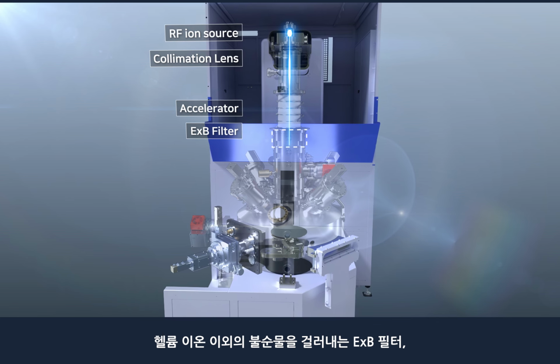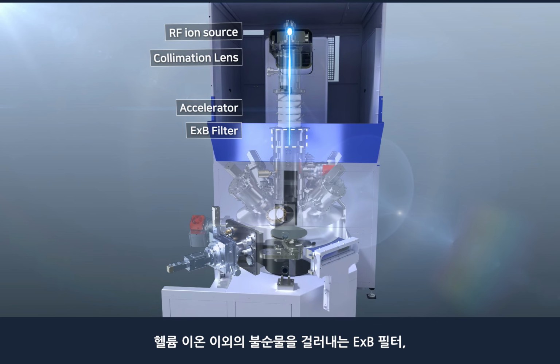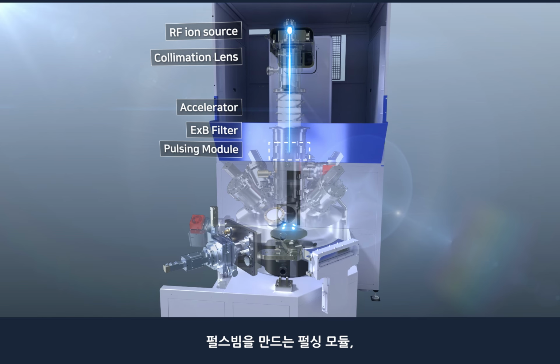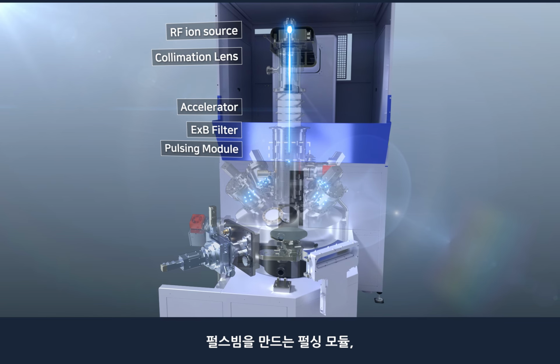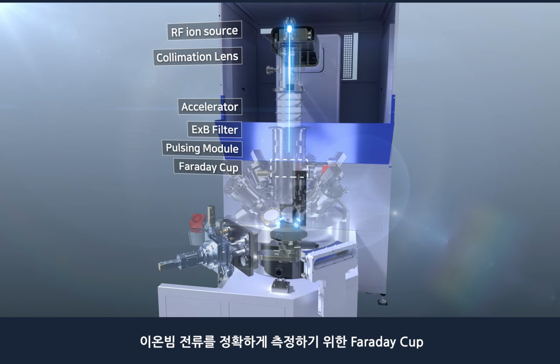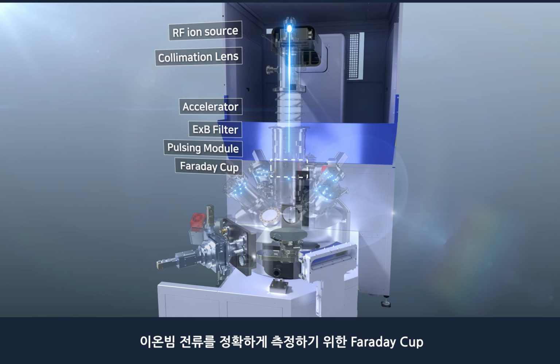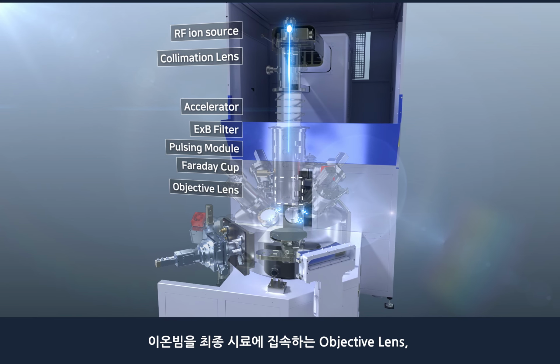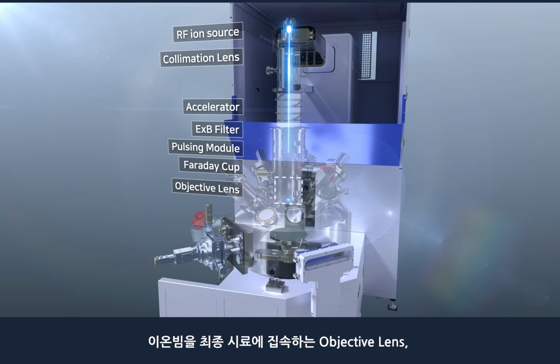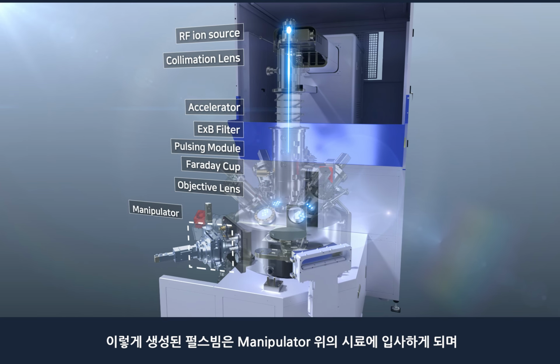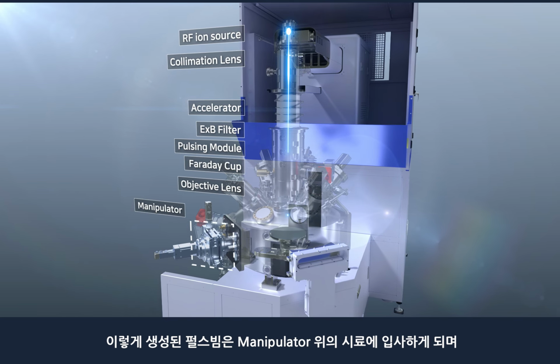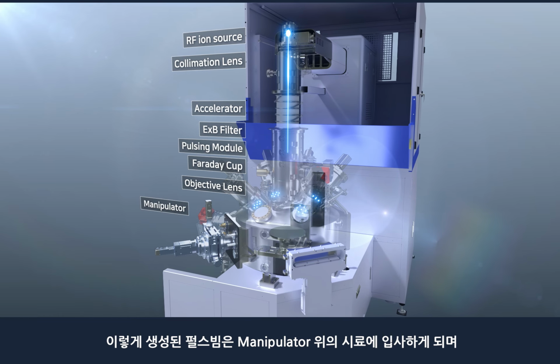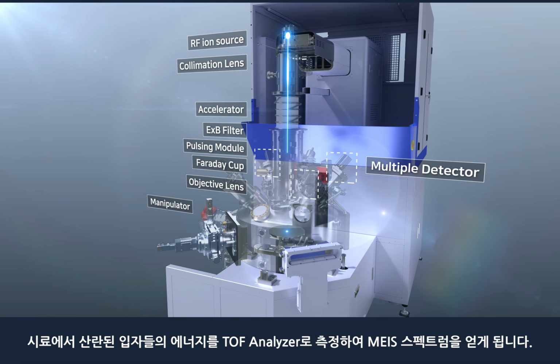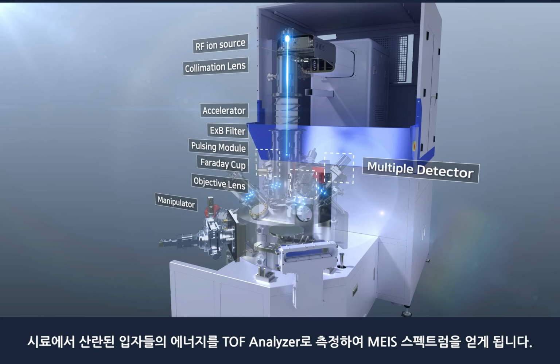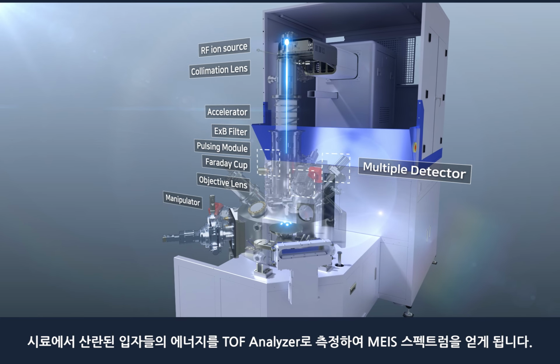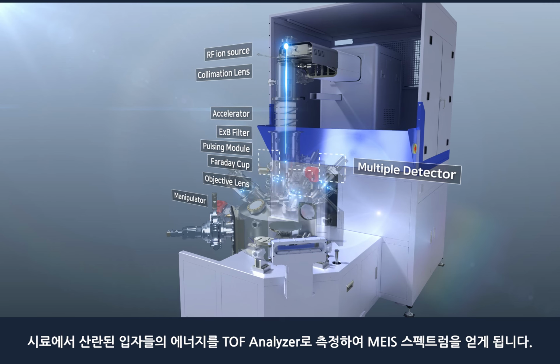an E-cross-B filter that filters impurities other than helium ions, a pulsing module that generates pulse beams, a Faraday cup for accurate measurement of ion beam current, and an objective lens that focuses the ion beam on the sample, and generated pulse beams are incident on the sample on the manipulator. The MEIS spectrum is obtained by measuring the energy of the scattered particles from the sample using a TOF analyzer.